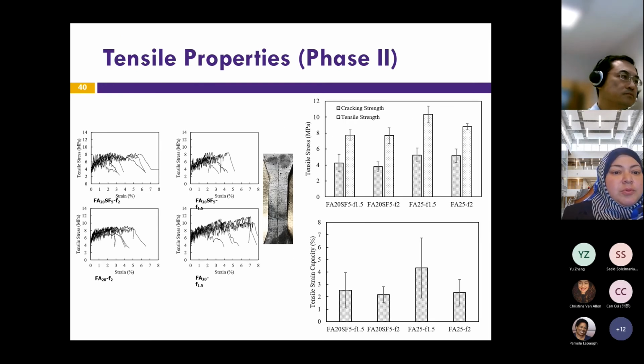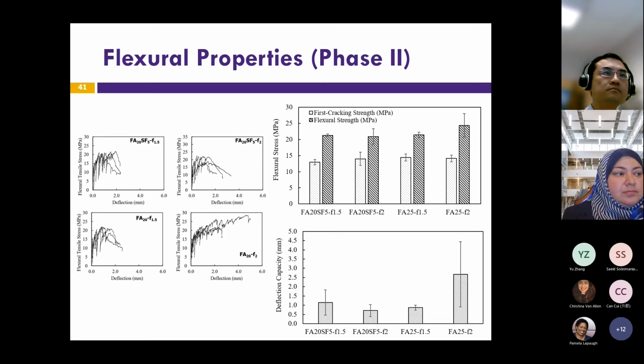Based on tensile properties, as you can see here, we see high ductility. We are getting the pseudostrain hardening effect that we are looking for. The mix with 25% fly ash and 1.5% fiber content had the best performance in the tensile test, and it had the highest tensile strain capacity.